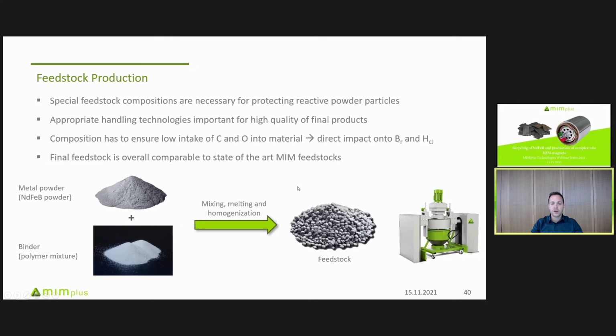In the feedstock, the polymers protect the powder, and it is quite comparable to state-of-the-art MIM feedstocks. But critical here is to use appropriate binders and appropriate technologies to mix the powder with the polymers without reaction of the powder with the carbon or the oxygen, because it has a direct impact on the remanence and the coercivity of the sintered permanent magnets.